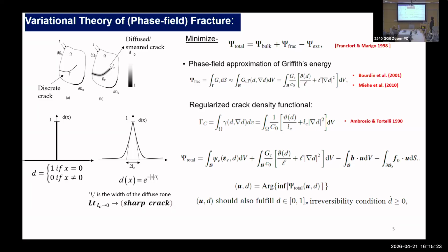Now, by the introduction of this smoothing phase field variable, we can further approximate this fracture energy, which was originally cast over a surface area term, now integrated over a volumetric domain. And how do we do that? We basically introduce something called a crack density functional. You can just think of it like a strain energy density functional. Okay.